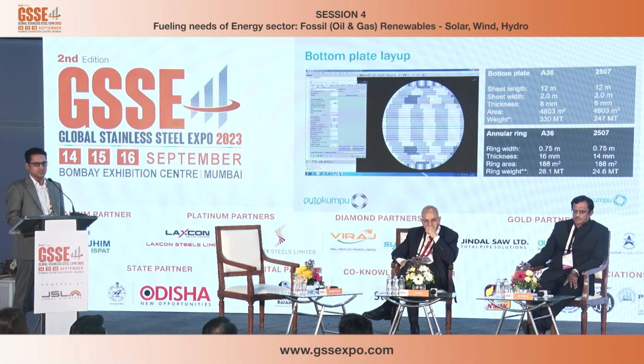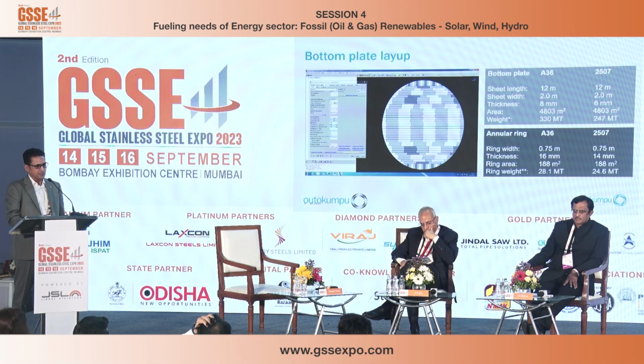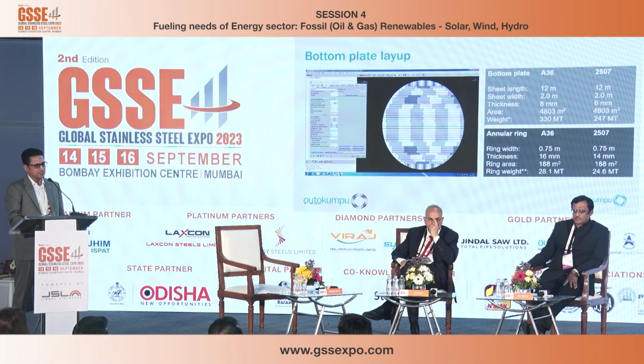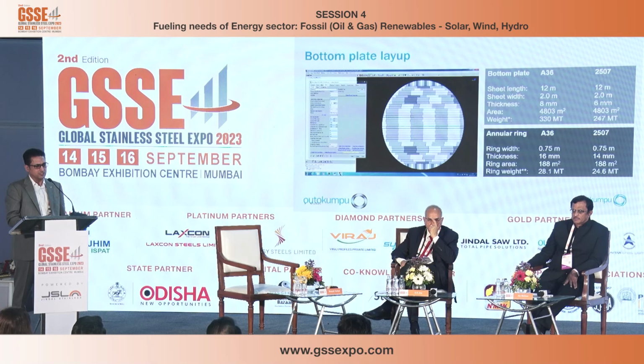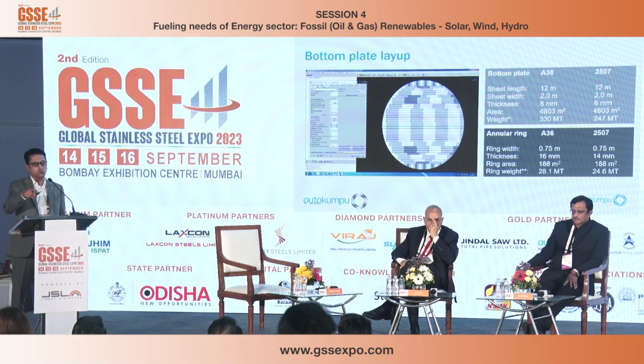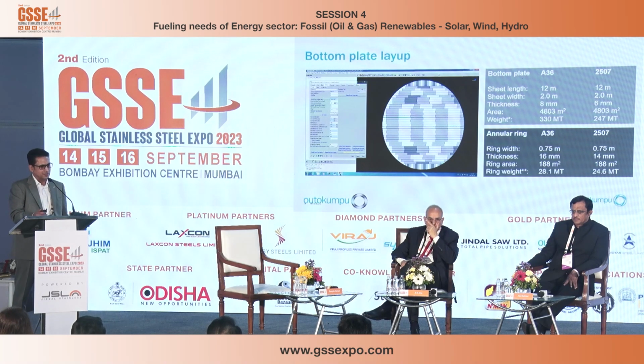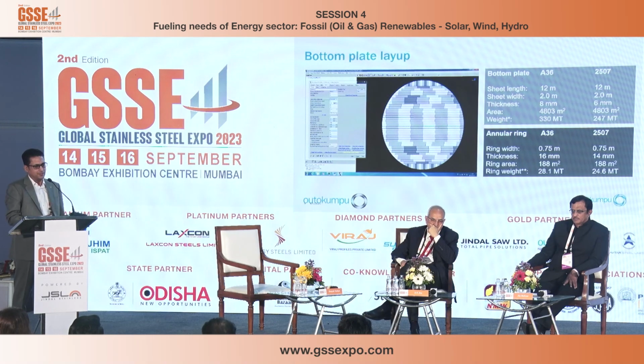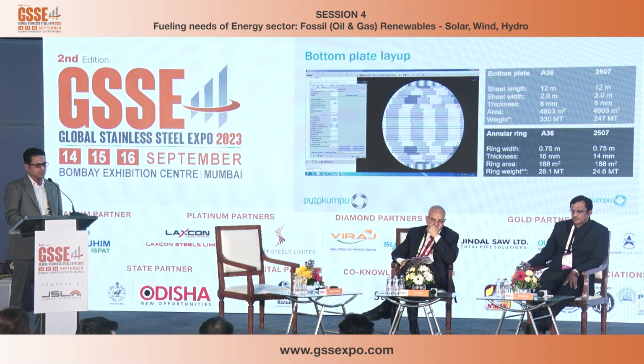The bottom plate, as I said, comparing A36 carbon steel versus Super Duplex 2507. Length of the sheet 12 meter in both the cases. Width of the sheet I have taken 2 meter on the same side, both the grades. Thickness 8 mm in A36, which is the design actually used, but when you go to the Super Duplex stainless steel, you can use the strength of the material, which is 500 megapascal plus. You can reduce the thickness to 6 mm. In fact, you can go to 5 mm also, but the design standards of code don't tell you to go lower than 6 mm. Area, if you work out mathematically for A36, it is 4803 meters square.